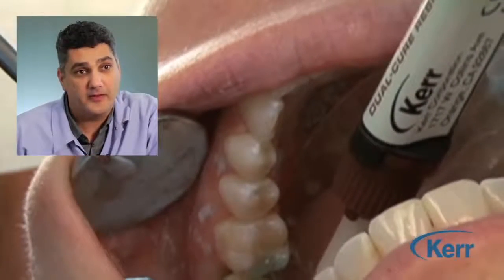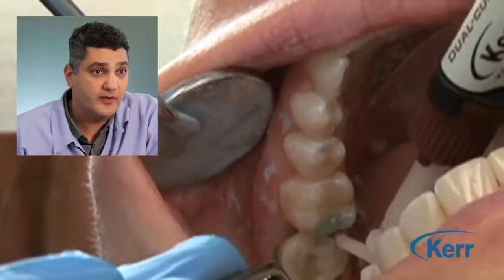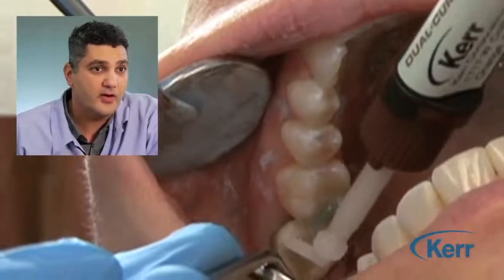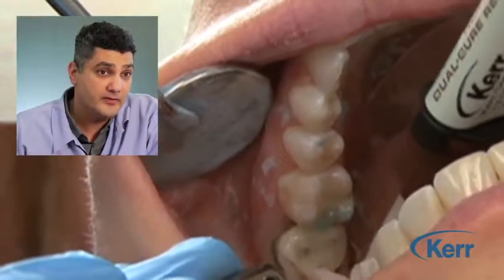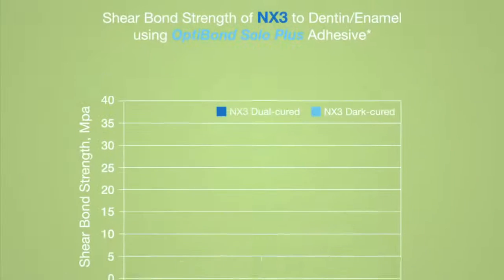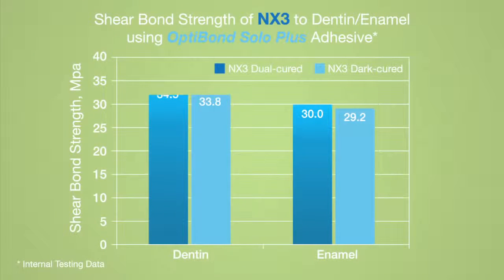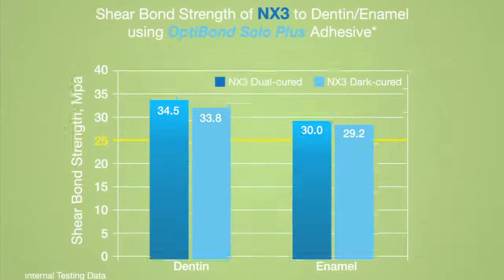The ease of cleanup, the color stability, and the long-term results I'm seeing on these restorations on recall really make NX3 my resin cement of choice. Looking at the shear bond strength of NX3 to dentin and enamel using OptiBond Solo Plus, you can tell that it's well above the accepted range of 20 to 25 megapascals. Generally, the industry standard is if you're above 25 megapascals in shear bond strength, that's a very acceptable cement to use for bonding restorations. You can clearly see NX3 is well above that range, both bonding to dentin and enamel.